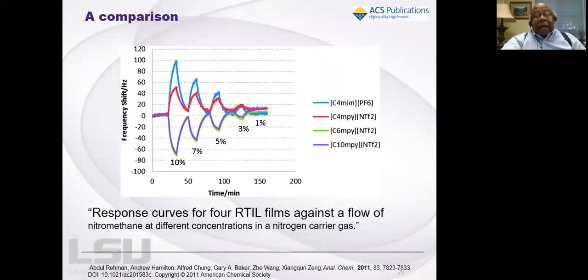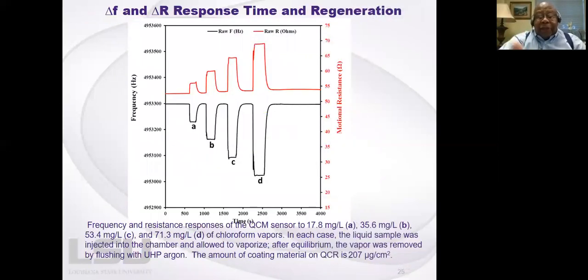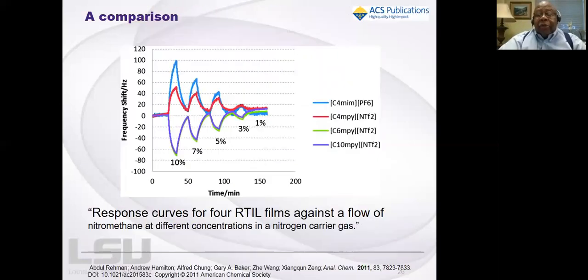This is not our system, but notice here, over the time frame, time per minute, this is the kind of response that other people would get. You will never reach a plateau. Whereas if you look at ours, we reach a plateau in a very short time period. These are in seconds, whereas the one that we obtained from the literature, these times are in minutes, and they don't reach a plateau. So that says the response of our material is very rapid, and it clears out very rapidly.